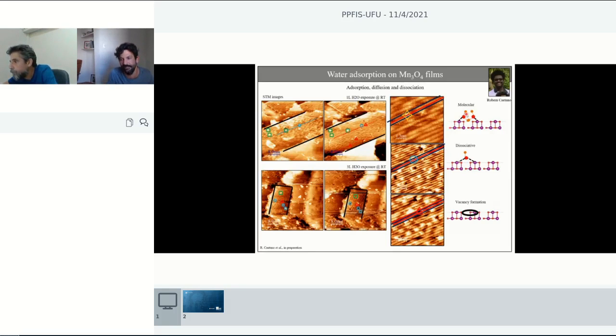And then we can say, if we have in the beginning some kind of what appears to be molecular adsorption, and then later on, as you dose more water, or you change the temperature, or you just let the kinetics go on, so time goes by, then you see that the water can dissociate from different protrusions, and then finally it can leave the surface. Then we can try to think about which kind of species were on the surface, and how this affects the reactivity of this surface.